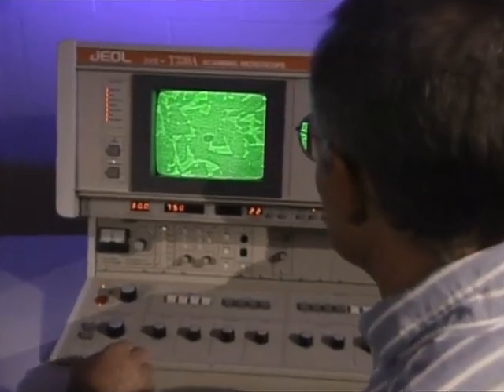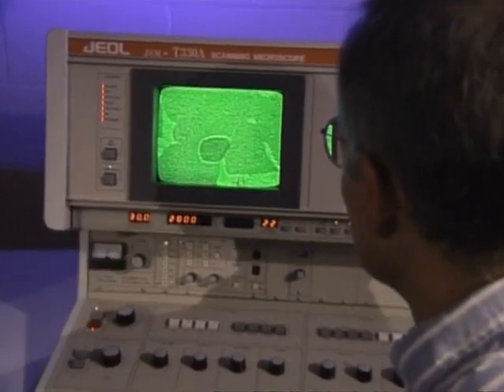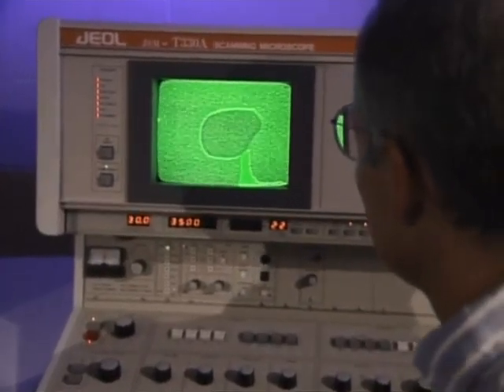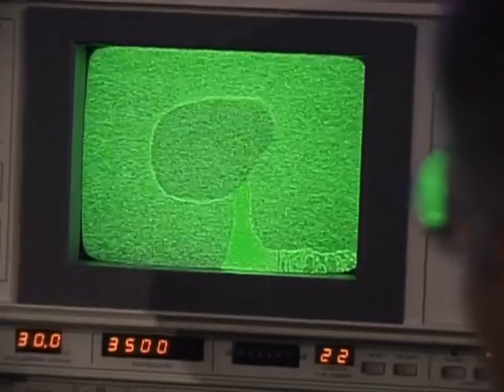Higher magnification shot. Lots of ferrite, pearlite, big inclusion. That's a big one. Probably big old manganese sulfide. That's a big one. Big manganese sulfide. As they suspected, the steel is full of large manganese sulfide inclusions, chemical imperfections that create weak areas which cause the steel to be brittle.